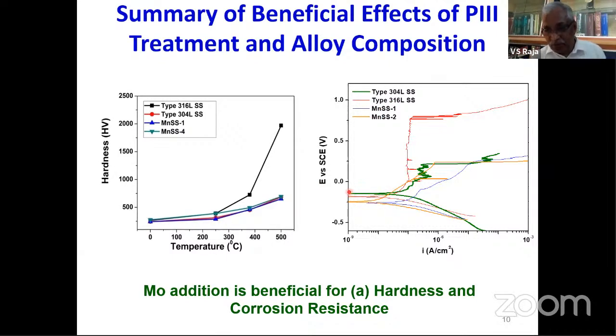For example, what's shown in this curve is potential versus current. What you see here is when I raise the potential, the current does not increase. We call this a passive region. The stainless steel has a huge amount of passivation taking place because of this. Again, not all the stainless steels are the same, right? 316, 304, and a manganese-containing stainless steel. Not all of them behave in the same manner.